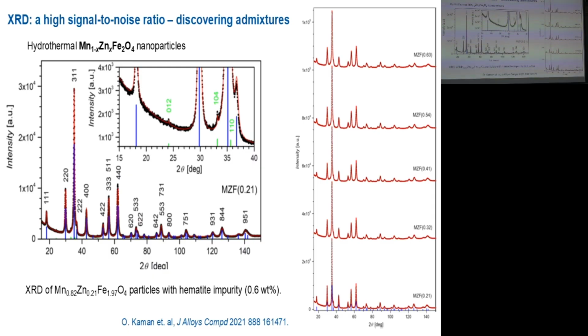In this case, it was less than 1% of hematite in the ferrite sample, and I would say that this is not a shame. It is not a shame that the sample is not pure. If someone had measured this sample at low quality, then it would have been a pure sample. But if you measure it at high quality, you will reveal something like this. So please be careful when doing powder XRD and try to collect nice data.